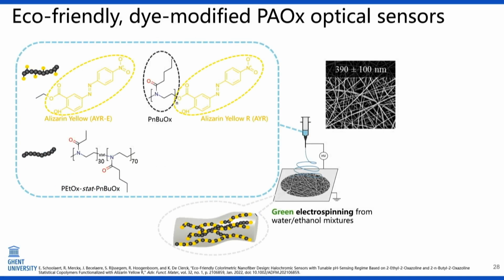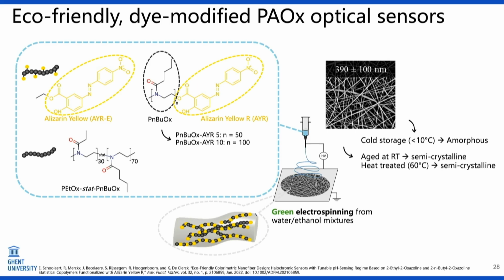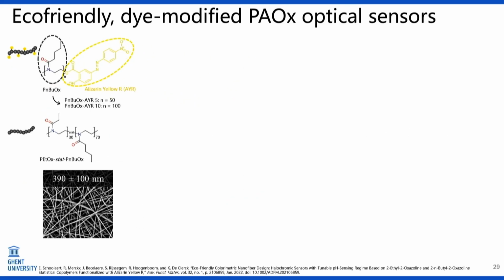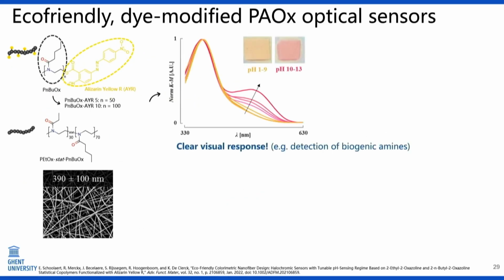For this application, we used the water-stable polyoxazoline, the statistical copolymer, with a single dye, here alizarin yellow. By modifying the dye with different sized PEtOx groups, we could change the pKa value of that dye. Then we can combine both by just electrospinning in water, and because of the length of that PEtOx, we have no dye leaching anymore. We can keep the membranes amorphous or turn them into semicrystalline materials as we want, depending on the application. And once we've made those membranes, we can see a very clear, very rapid visual response, for instance for the detection of biogenic amines. We can tune the response time from minutes to seconds, depending on the crystallinity of the polymer.